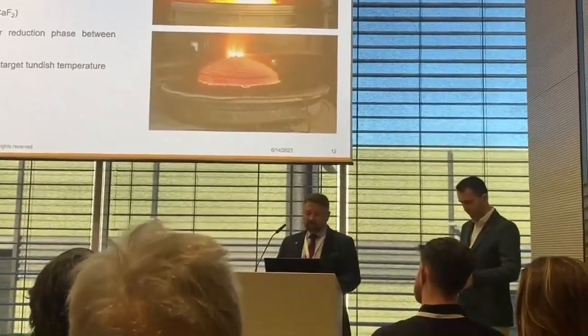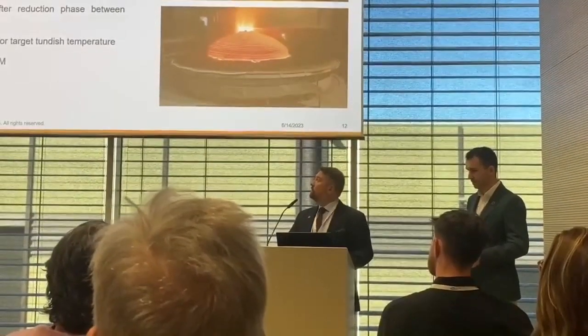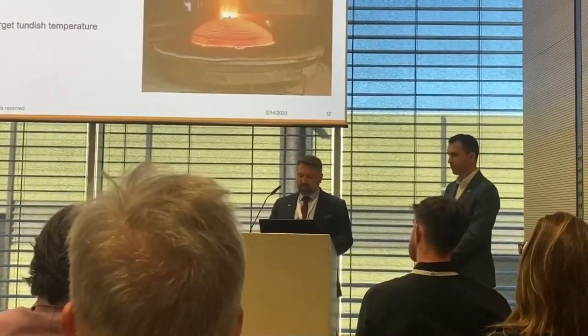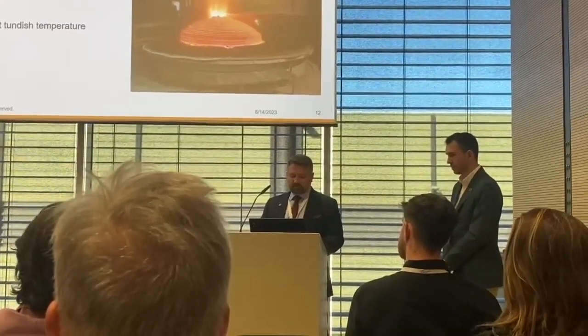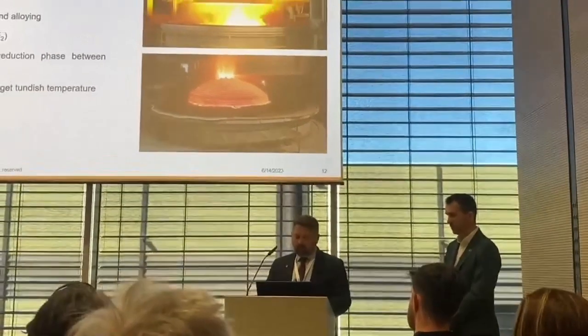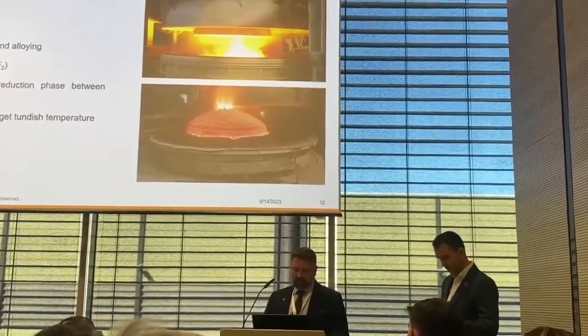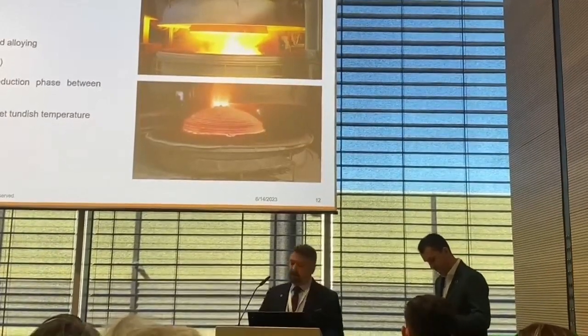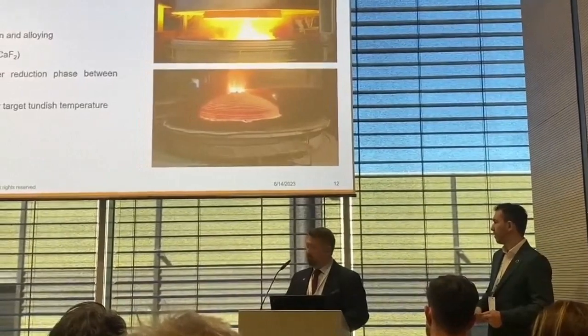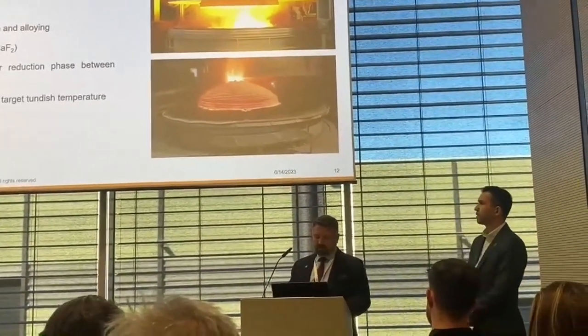The deoxidation was done by the addition of ferrosilicon for chromium reduction at the end of the VOD process. After lime and fluorspar addition, in order to adjust the slag viscosity, the cover was opened. Ferrosilicon, low carbon ferromanganese, and all the other alloy elements were added according to the required analysis. Also, cooling scrap was added to reach the aiming temperature.